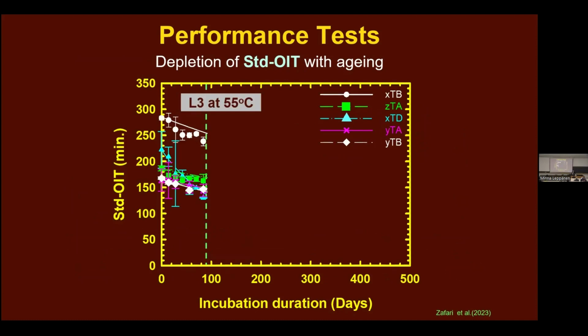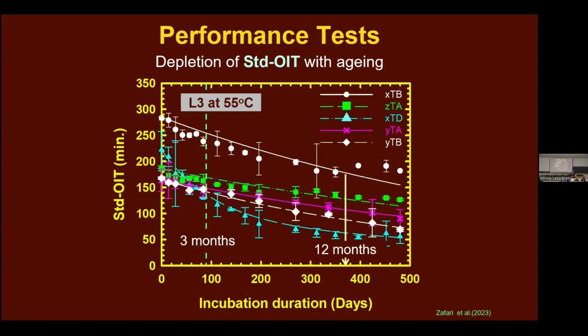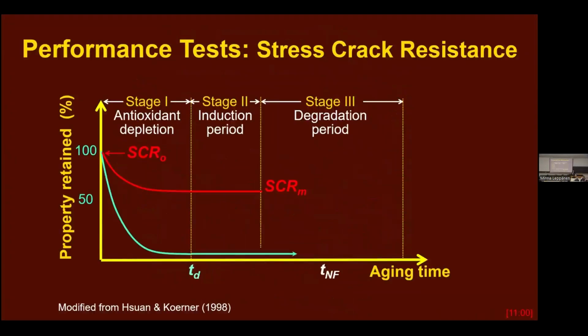Here is a different temperature and 5 geomembranes in the one solution. They all start at different points, initial values, but you can see that some perform much better than others. Blue started second best and is not doing too well. White started best and is doing pretty well. Green started in the middle of the pack and is doing second best. You can't predict what's going to happen without doing some testing.